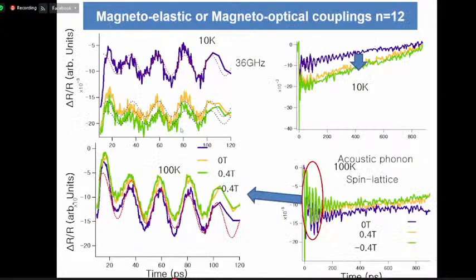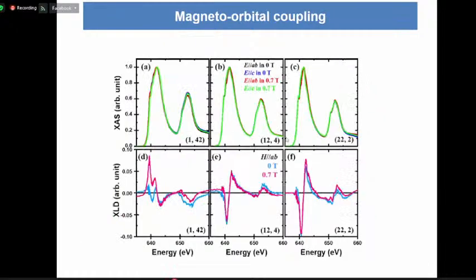This oscillation also responds to the magnetic field. Above the Curie temperature, with or without magnetic field, it's almost similar. But below the Curie temperature, with magnetic field is different from without magnetic field. So this phonon oscillation is also related to the magnetic field. It's interesting. We found some orbital structure is correlated with the magnetic field as well.